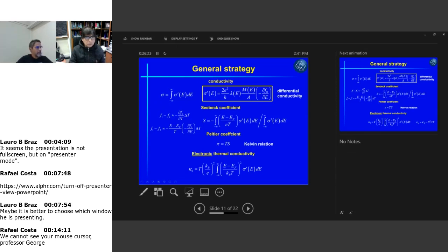And the reason for that is that, again, for the electronic thermal conductivity, the driver here is a difference in temperature. So I do the same thing I did here to write F1 minus F2 as the derivative of F0 with temperature. I change the expression to the second expression here below. I gain an E minus EF, but what is being transported here is exactly E minus EF, the difference in energy between the level E and the Fermi energy. That's the energy that is being transferred. So I gain E minus EF to E squared. I multiply by KB squared, divide by KB squared, and so on and so forth, and I get this expression for